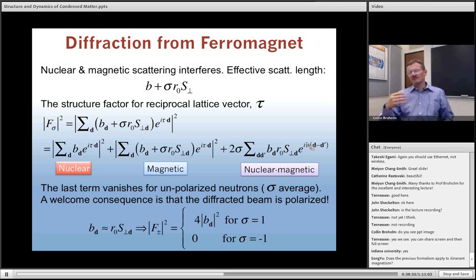But to tell you the truth, experimentally it's pretty difficult to pick that up in the form factor, because you end up being really dominated by the tendency of the dipole moment to actually be localized around the atoms within some sort of tight binding description. So this would hold both in the case of transition metal ions and certainly in the case of rare earth ions. So for rare earth ions, the spin density is really quite well localized around the atom.